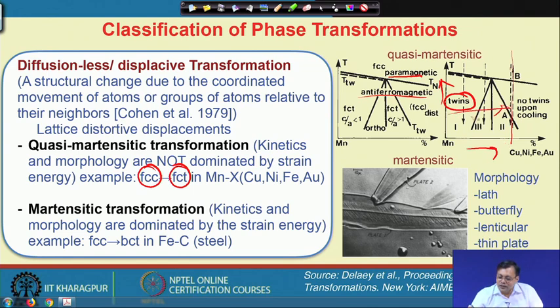There is a limit of composition beyond which that particular quasi-martensitic transformation does not appear, and these are mostly twin involved in this process. But you may also tell me, sir, in case of martensitic transformation there is also twin involved. Unfortunately, all martensite does not involve twinning. So, this is something new we will learn today. Let us continue with the martensitic type of transformation.